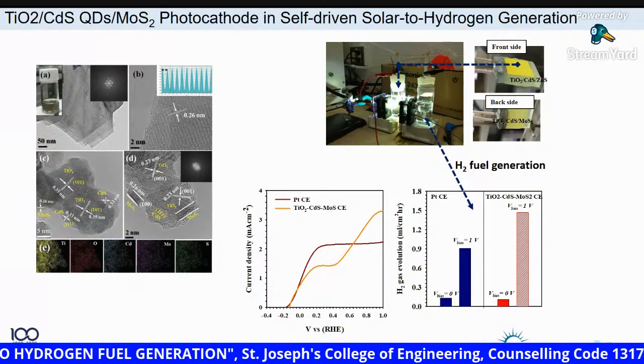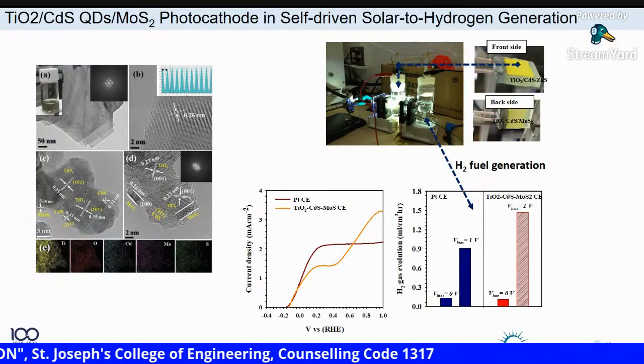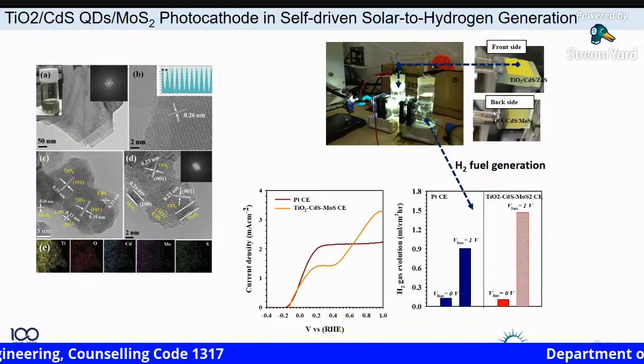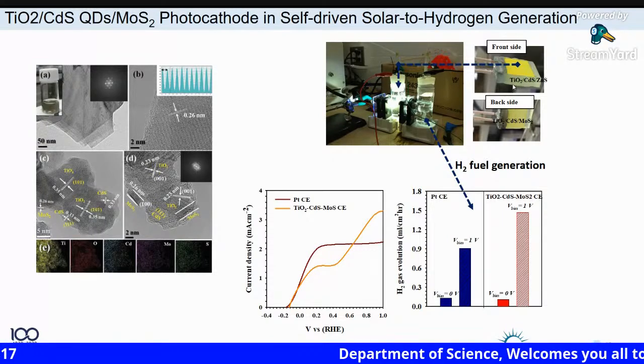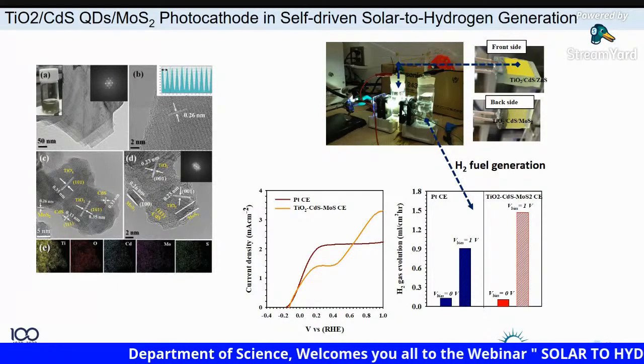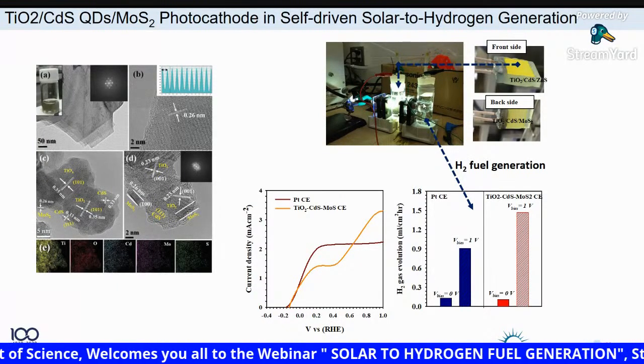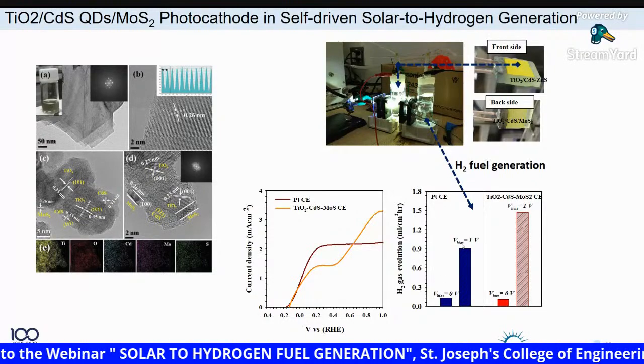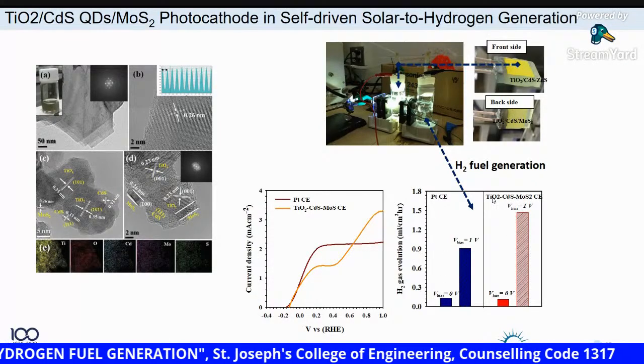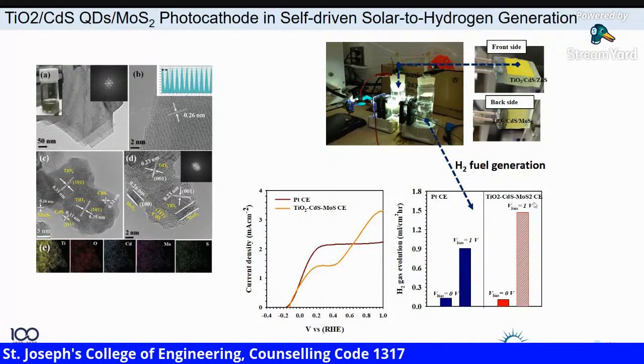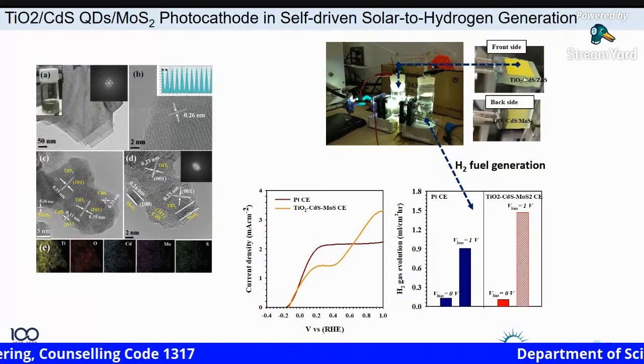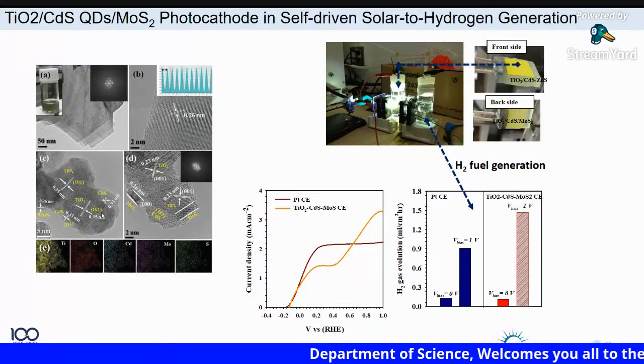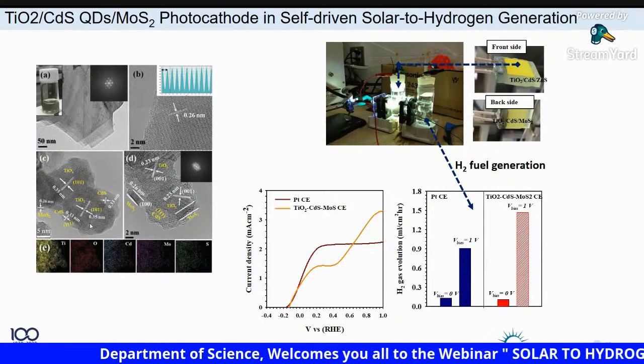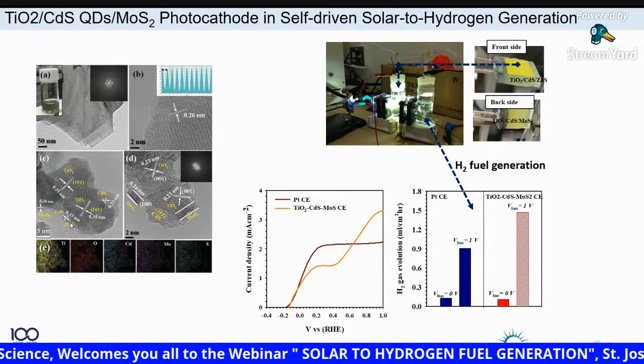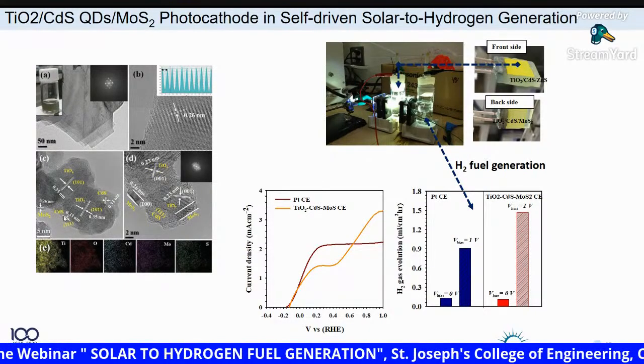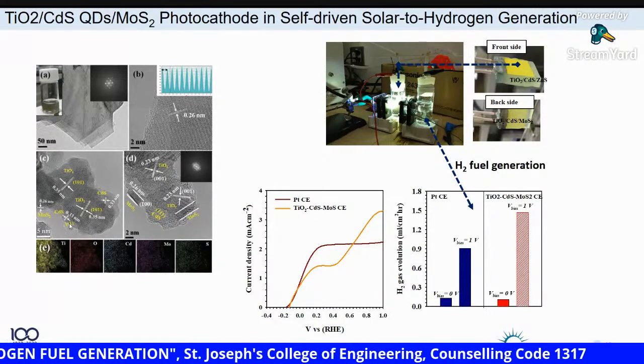So this is the conventional platinum paste. We just removed this Nafion membrane and everything, and then put one small artificial leaf type structure inside here, and then we tested the water splitting process. And you can see here, compare the platinum and our proposed titanium dioxide coated with cadmium sulfide and molybdenum disulfide. If you want to see this material with the naked eye, you can see the high resolution transmission electron microscopy. The inside is titanium dioxide, and small quantum dots of 4 to 5 nanometer size are coated on the outer surface of the titanium dioxide.